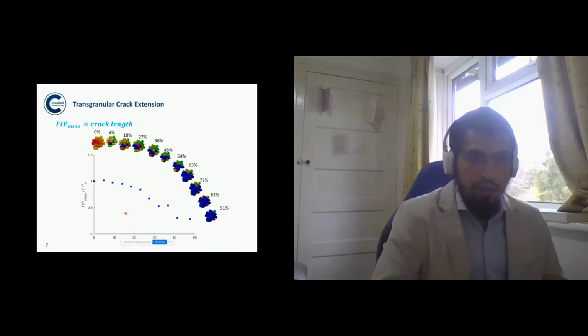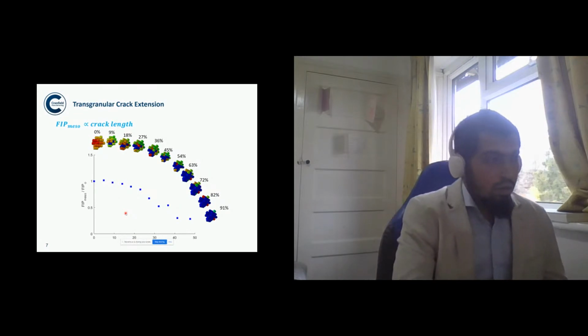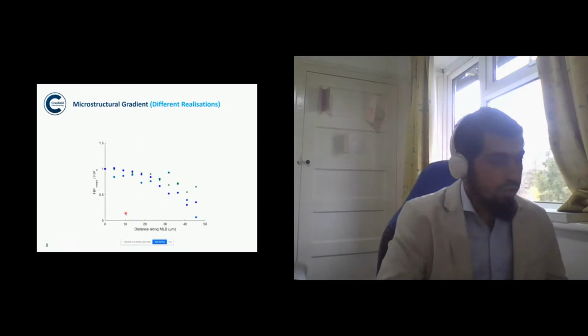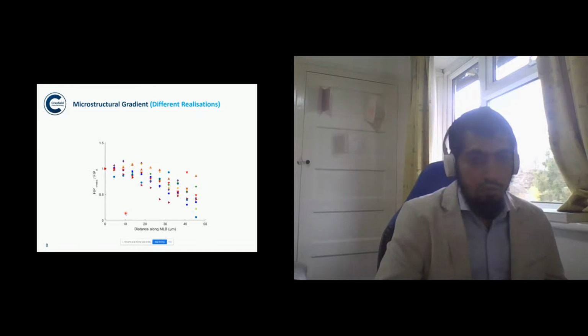And this shows that the driving force has a decaying trend as the crack extends in the grain, which is similar to the literature findings. So this result corresponds to one realization, one set of microstructure. We repeated the same set of simulations with a different microstructure, and interestingly, we found that this decaying behavior of the driving force as the crack extends is consistent. So this is normally termed the microstructural gradient.